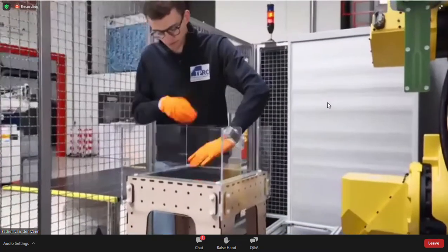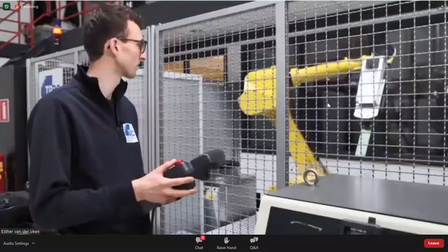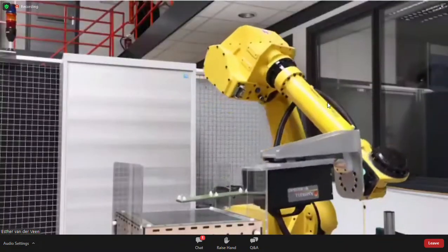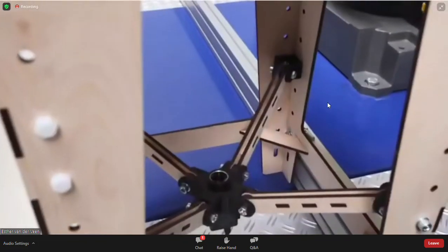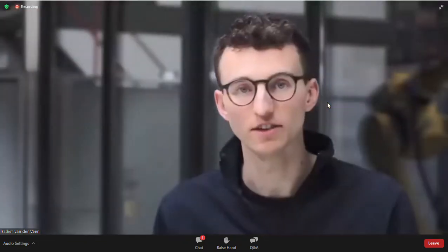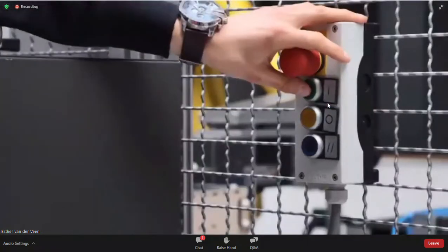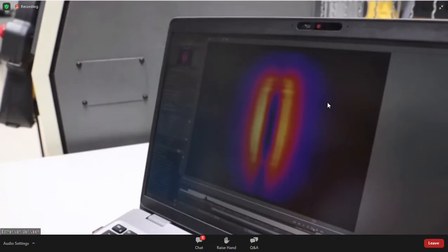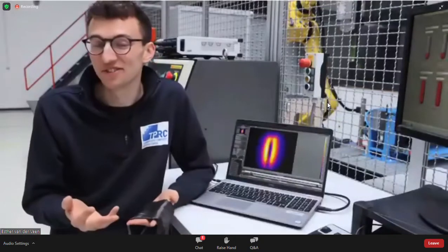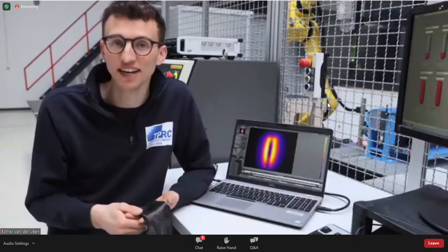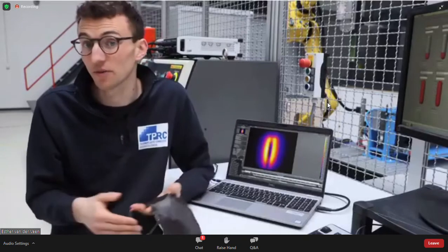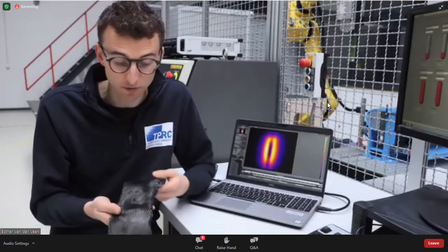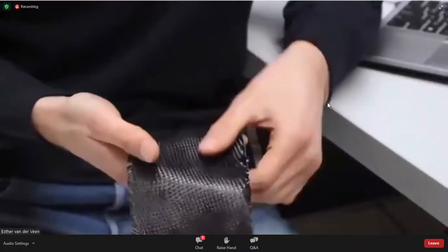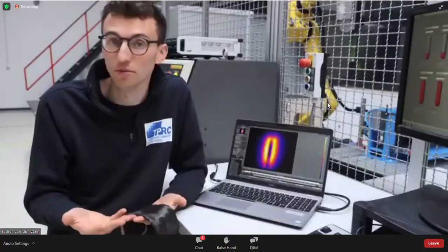I can show you the actual heat generation through eddy currents with an experimental setup that I built for my research. In this setup, we use a thermal camera to monitor and record the heat generation inside the material and display it on a computer. As we can see, the heat is generated very rapidly as the material heats up to over 100 degrees easily in a matter of a second. The challenge is to understand how exactly heat is being generated inside the material, and that requires a lot of fundamental research. The complexity is that we've got a network of conductive carbon fibers inside an insulating polymer.